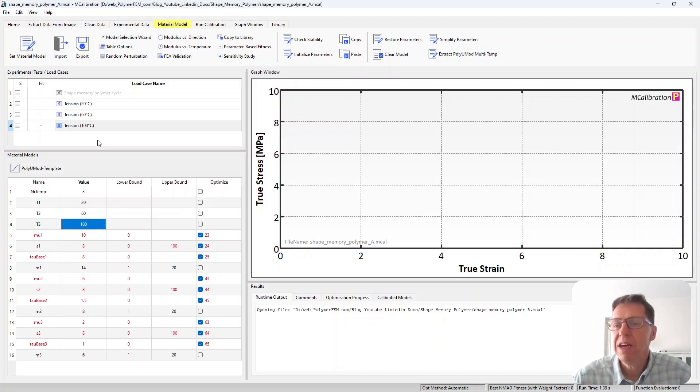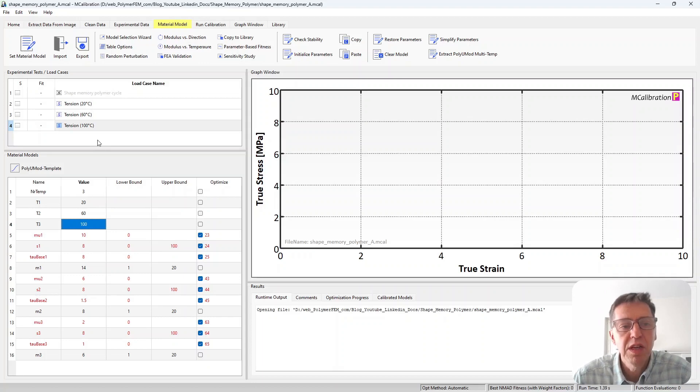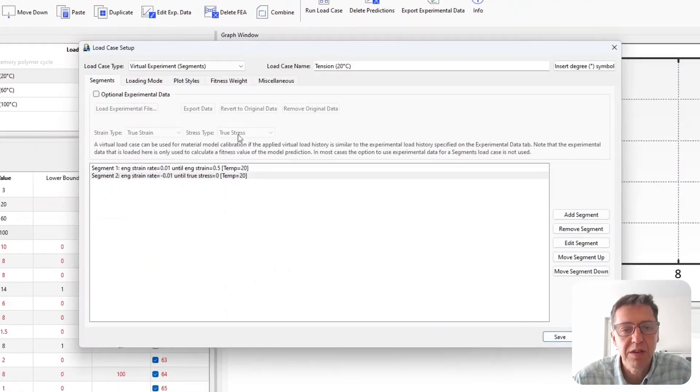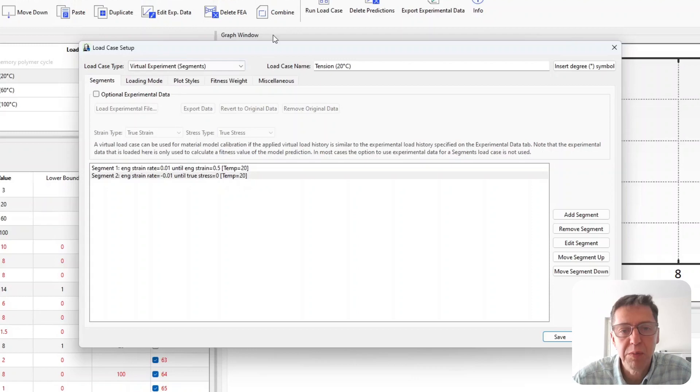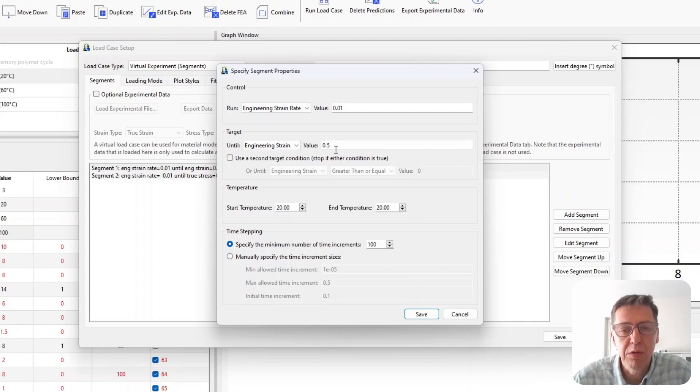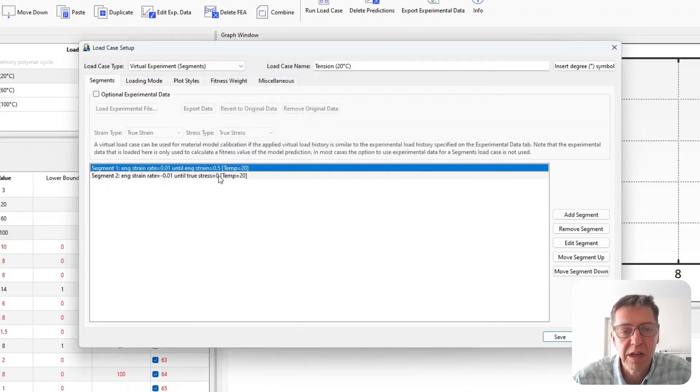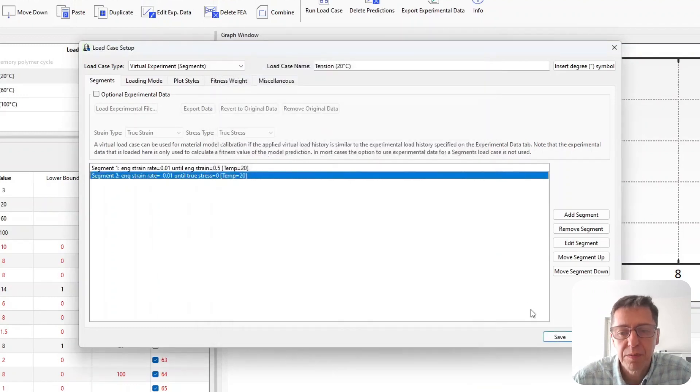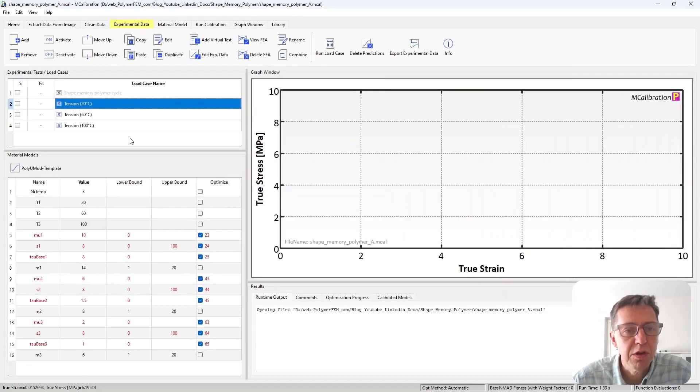Here I'm just demonstrating different materials. I don't have experimental data that I want to use. I'm going to instead use virtual experiments. So I go to the first one here, it's the tempered tension test followed by unloading at a given temperature. So it's a virtual experiment and it's at 20°C and I'm pulling it with constant strain rate to 50% engineering strain and then I unload it with the same strain rate to zero stress. And I do this in three different temperatures.